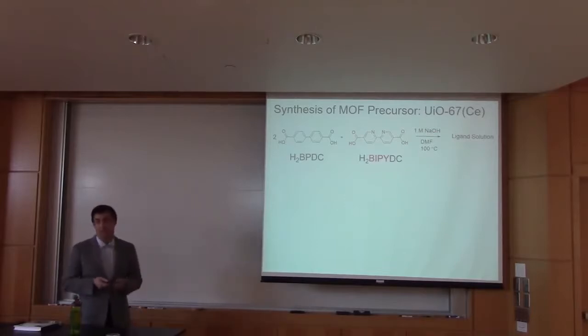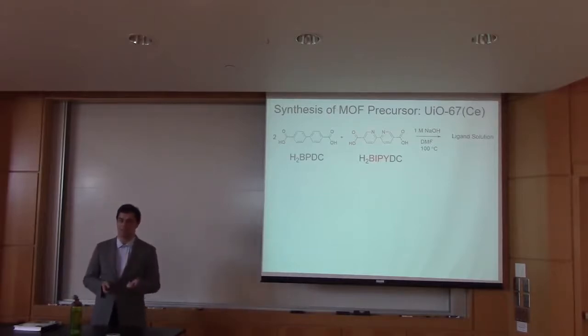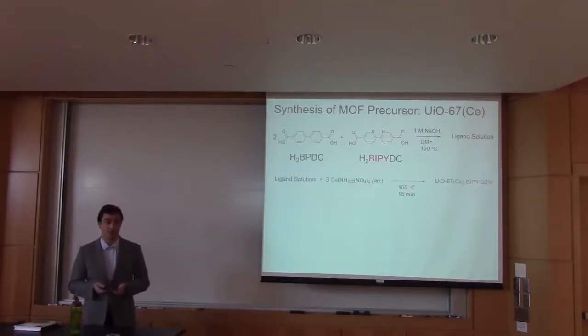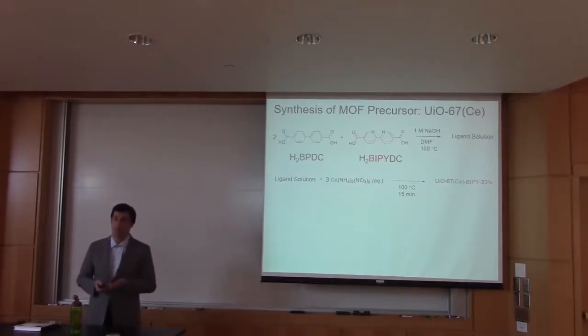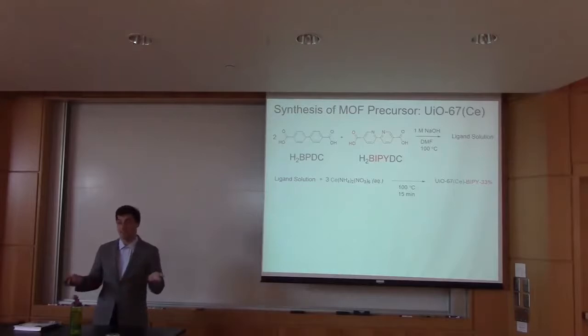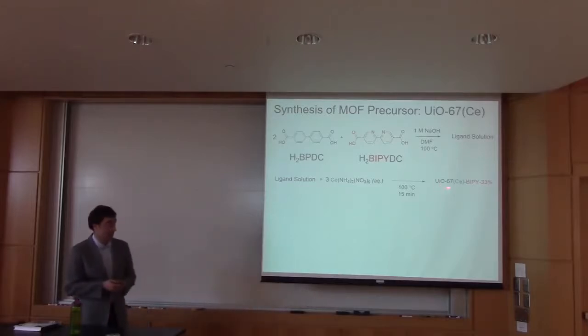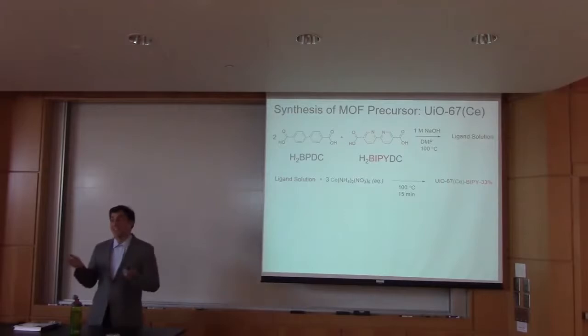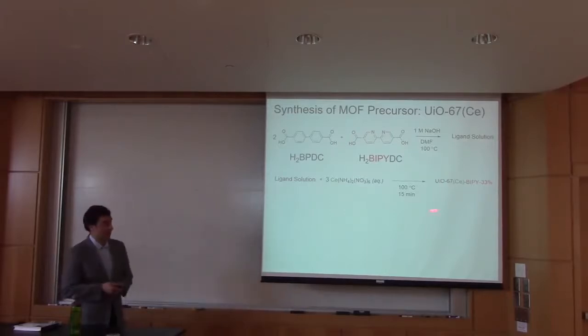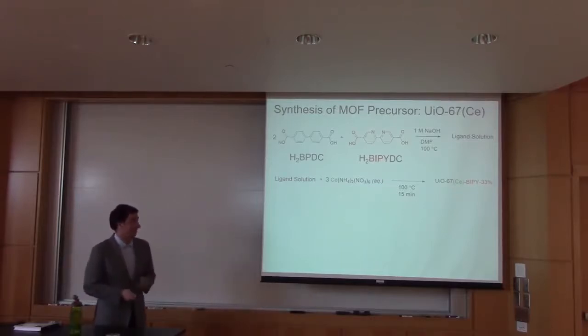Heating it in this organic solvent, DMF, at 100 degrees Celsius, and obtaining this viscous, milky solution, which is our linker solution, to which we're going to add cerium ammonium nitrate, which is our cerium source. And as soon as we add that, we have this bright yellow precipitate form. After an additional 15 minutes of heating, we have our desired MOF, which is UiO-67(Ce). But since we've added this secondary linking unit, we now want to denote that deviation from the original MOF as well, which is why we have this BiPY 33%. It's going to be one more add-on, but that'll be it.